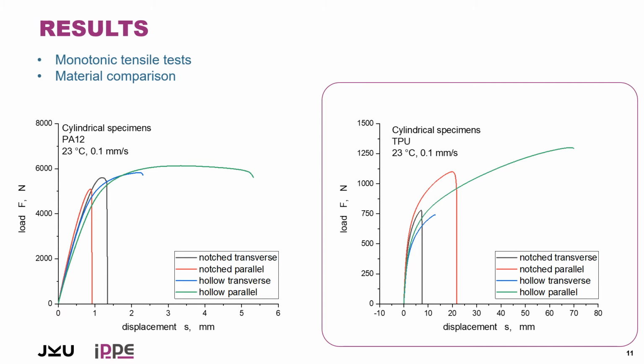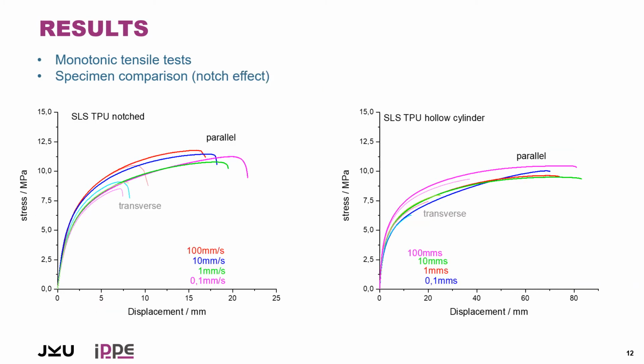Also, of course, we can see the difference between polyamide and TPU. The thermoplastic polyurethane materials are softer, reveal lower modulus values, but as you see, there are significantly higher fracture strain values. Hence, and because this is also my favorite material, we deal with this material in this presentation.